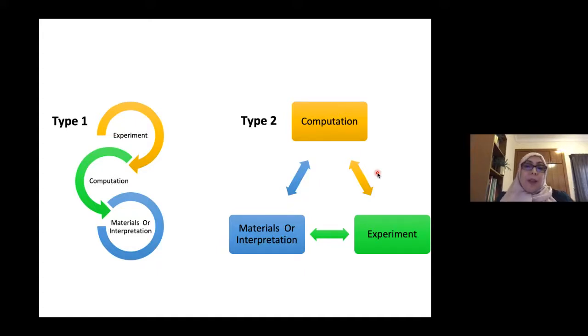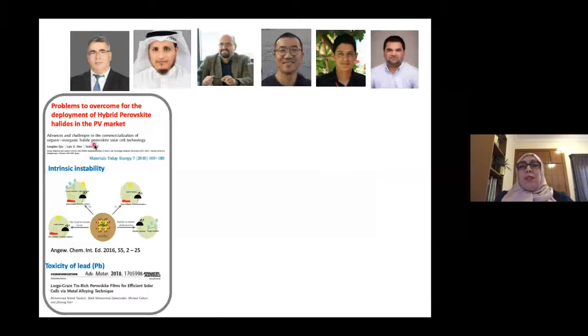The first thing I wanted to mention: in the previous talk, you mentioned stability, and indeed even the hybrid perovskite materials suffer from stability issues, because these are materials grown from solution processing at low temperature. So they are very prone to decompose under different conditions such as humidity, ultraviolet light, and oxygen. On the other hand, there is another issue: if you take methylammonium lead iodide, it contains lead, and a lot of people are raising the issue that lead might be toxic. So we took this challenge and looked at these two major aspects that put the technology at risk of being deployed at larger scale.